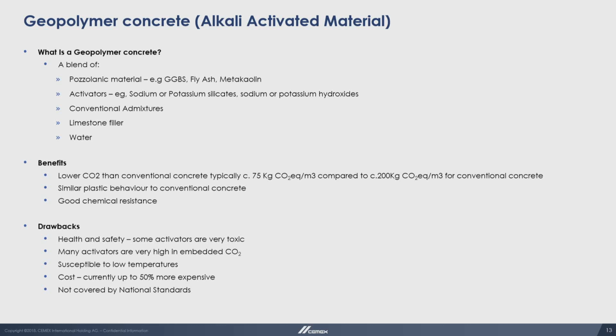What are the benefits of these materials? Well, they are lower CO2. There's no cement clinker in them at all. But don't be misled into thinking that these are zero carbon concretes, because they're not. There is carbon in slag, for example, and the activators themselves are very, very high in CO2.